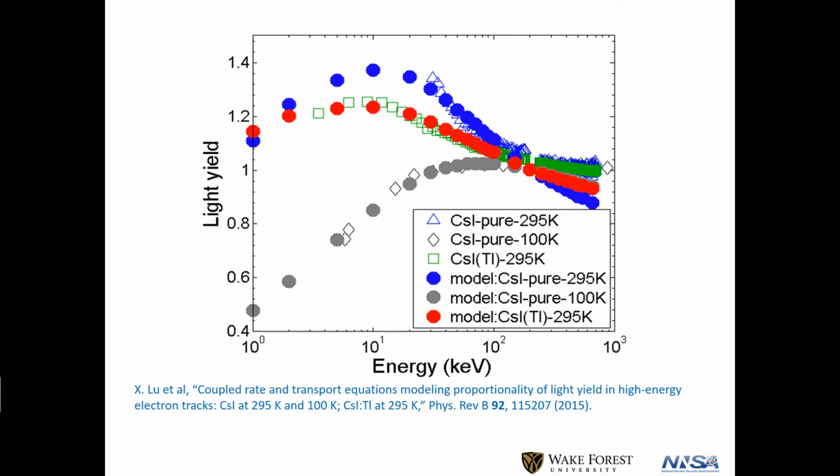Okay, so here we took the same material at changing temperature and putting in the dopant. And then we got the model, the same model, with one set of parameters, many of them, in fact, coming from independent experiments. Pretty good agreement. So we think we're on the right track. We're not totally satisfied, because we were modeling a pretty non-featured curve, and we're doing it with 27 parameters. Not all adjustable, but there are 2 or 3 that are adjustable. So not real satisfactory, and we realized there's a better way to do it.